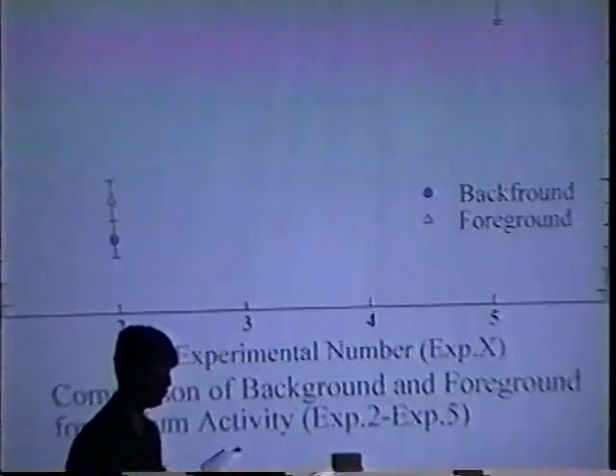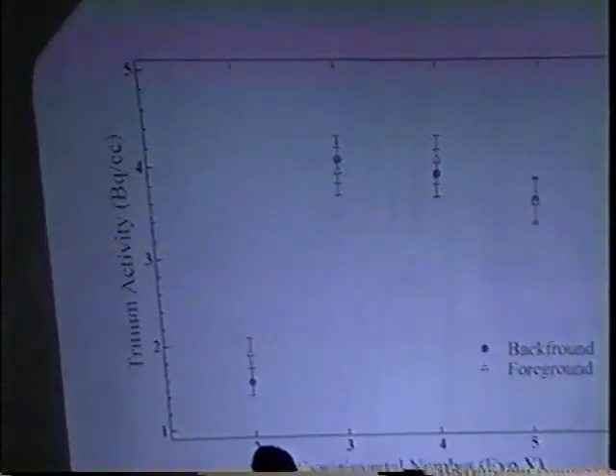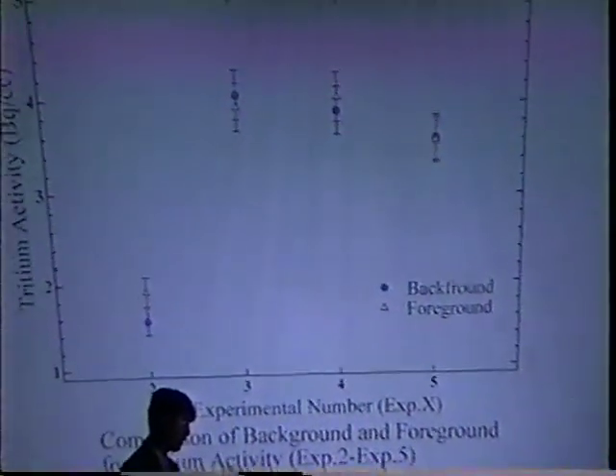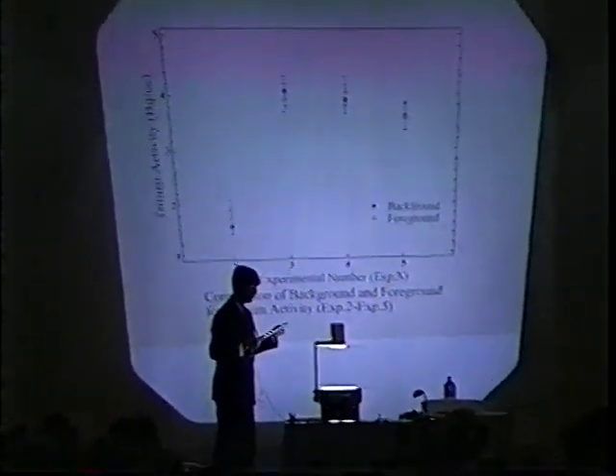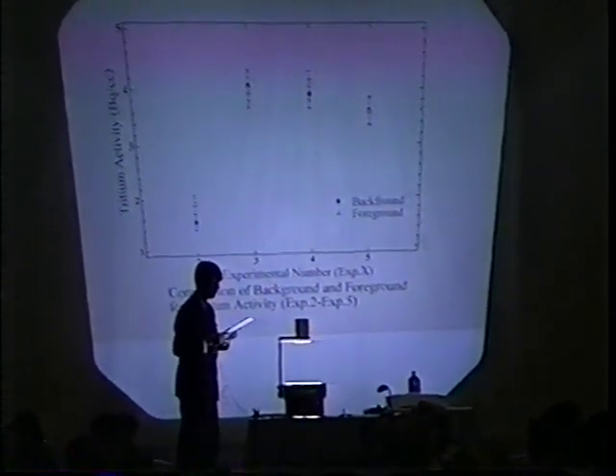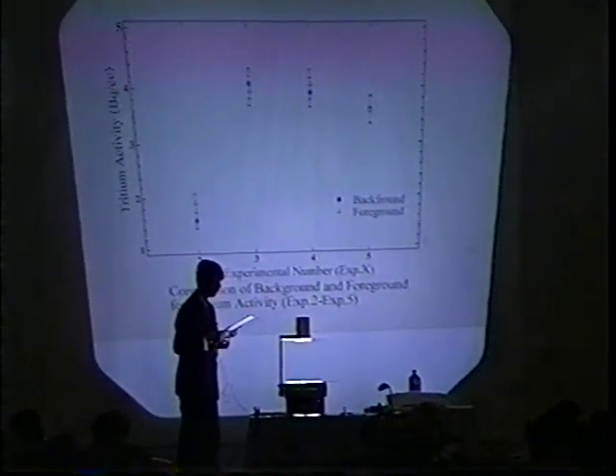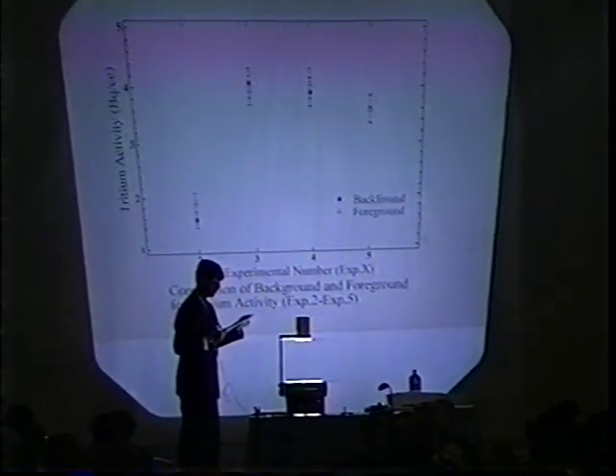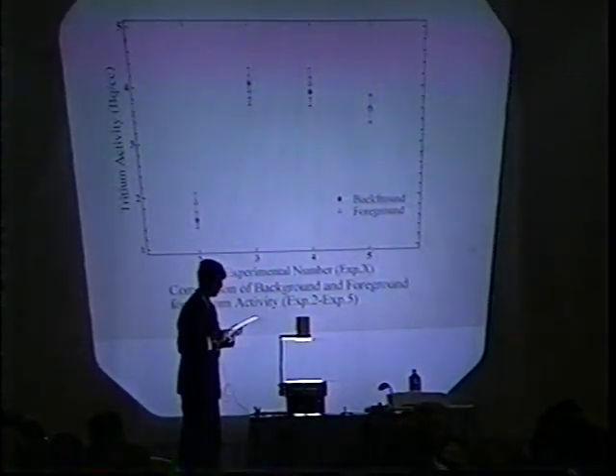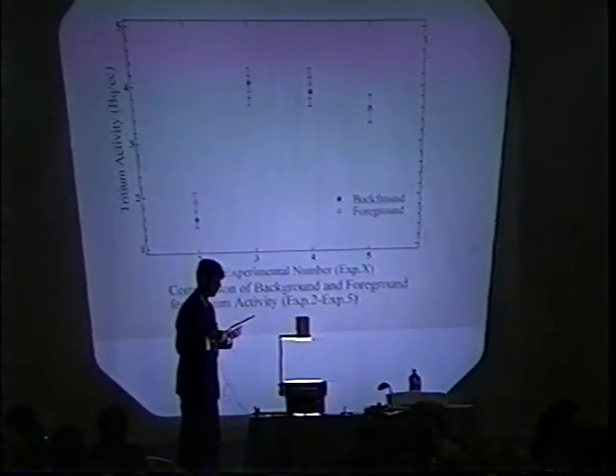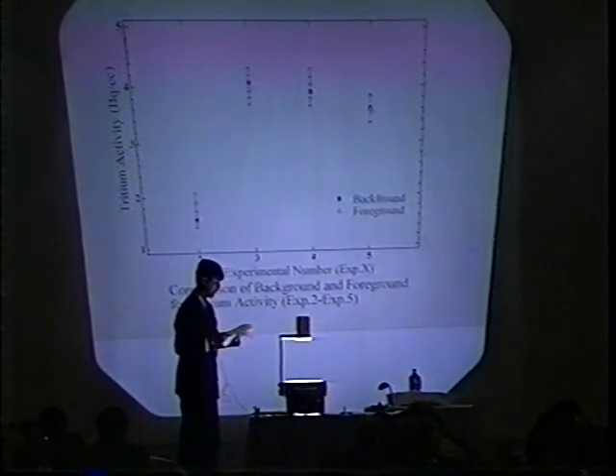In all the experiments, a clear increase of tritium in the electrolyte was not observed. This shows results of tritium analysis in experiments 2 through 5. Tritium activity of the electrolyte before electrolysis was defined as background and that after it as foreground. There was a difference in tritium level between experiment 2 and those from experiments 3 to 5, because the electrolyte was exchanged to a new one after experiment 2. Tritium concentration during the long electrolysis would be suggested because of selective absorption of the lighter isotopes, namely H and D, to the palladium plate.